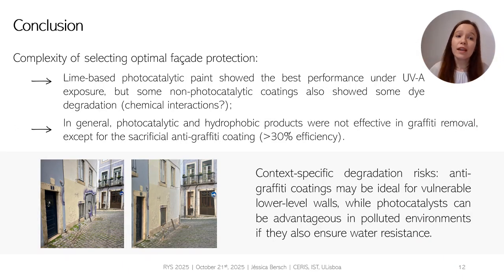From all of these results, we can conclude that there is a complexity to select optimal facade protection. For example, we could emphasize that although lime-based photocatalytic paint led to the best performance for self-cleaning, some non-photocatalytic coatings also showed some dye degradation, probably due to chemical interactions that could be investigated. In general, photocatalytic and hydrophobic products were not effective in graffiti removal except for the sacrificial anti-graffiti coating. So we need to find a balance, and maybe context-specific degradation risks must be considered. For example, anti-graffiti coatings may be ideal for vulnerable low-level walls, while photocatalysts can be advantageous in polluted environments if they also ensure water resistance.